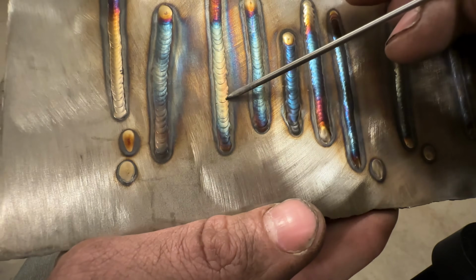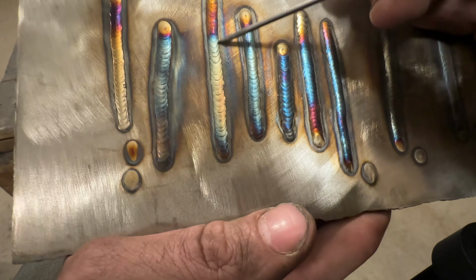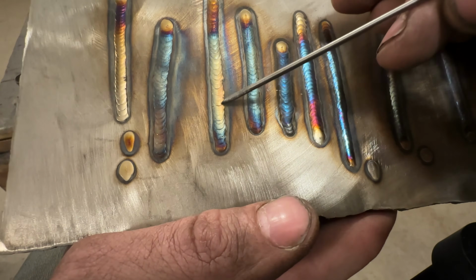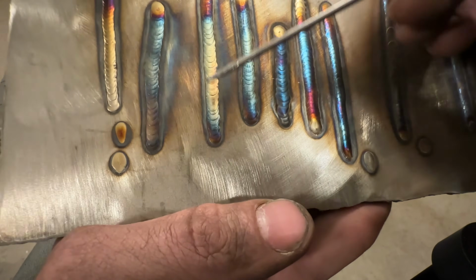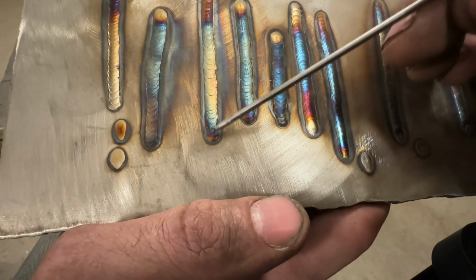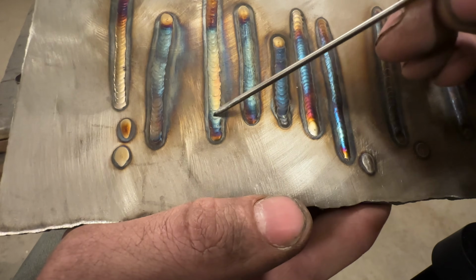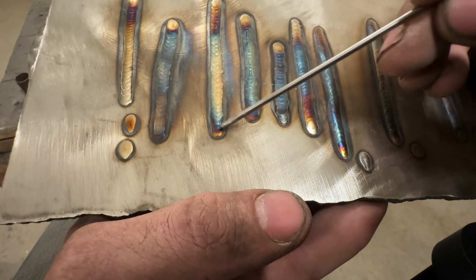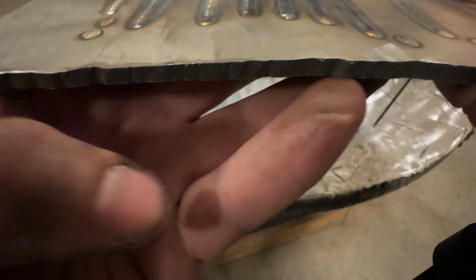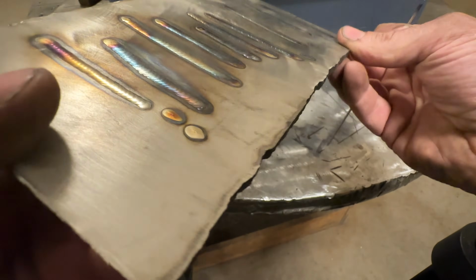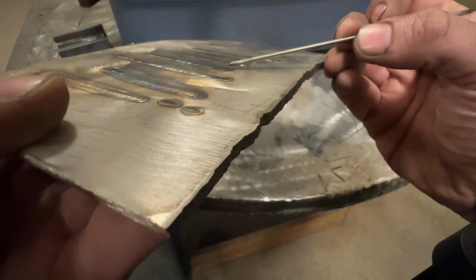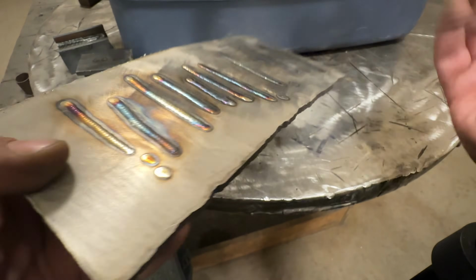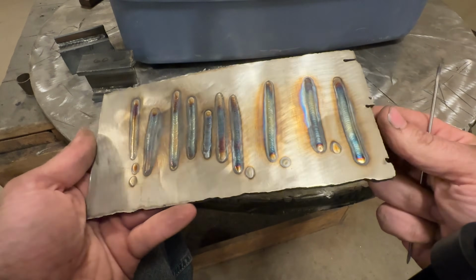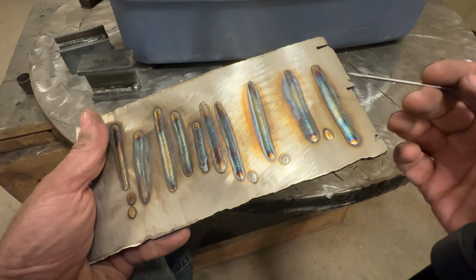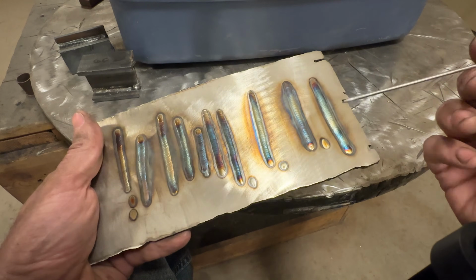When you look here, and I'll bring this way in here, you can see evidence of cold toes or just lack of consistency in TIG. It's just so much more minor than what you see with stick and MIG. You still see the same evidence. At the start, this is a little bit humped up, and then it flows out wider. This is because the amperage was too low, and then the weld got moving. And you'll see, it's going to be very difficult. This is more humped up here, and then it flattens out. But again, it really doesn't matter the material you're welding. All the signs are the same. It's just with stainless, the color tells you so much.